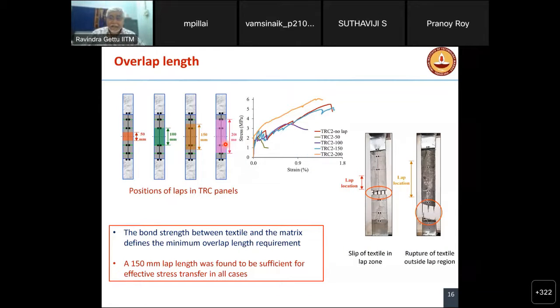Now when we do an element, we have to overlap the textile, just like we do splicing and lapping of reinforcement. So we did a lot of tests with different overlap lengths. This was done by my postdoc Komati, where she was looking at different lengths. And we found that if we have about 150 mm lap length, it was good enough. So that means when you have a long element, you should make sure that the textile is overlapping at least 150 millimeters.